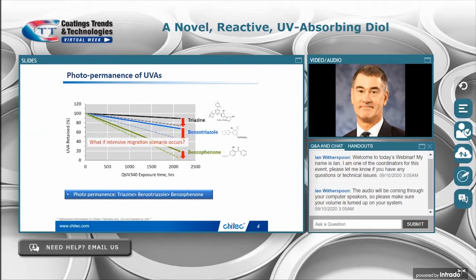These dotted lines that I just added are meant to represent the extra loss due to various migration possibilities. And of course, where that dotted line goes will vary by what the environment is and what the coating is exposed to. So in general, the triazine 5400 outlasts the benzotriazole family of UVAs, and you can see that in the diagram. And benzophenones are most fugitive and really aren't used for applications where you need very long-term, high-performance type durability.